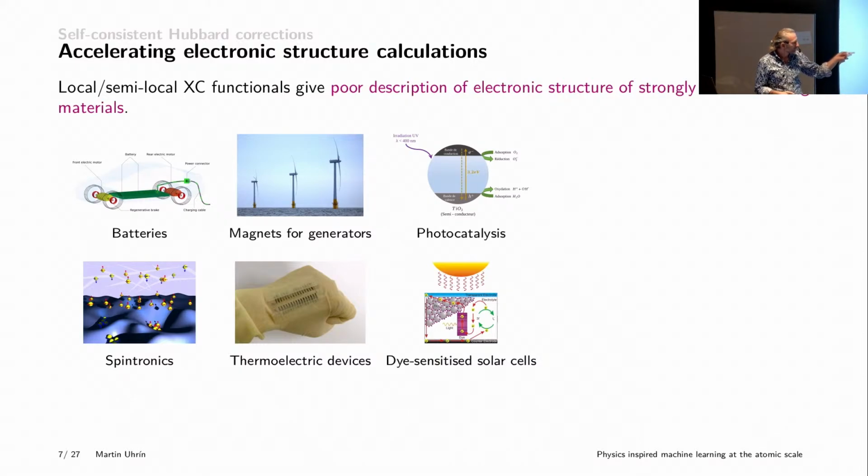One of the groups that I was in with James is very interested in electronic structure theory and pushing it beyond what it can do today. That obviously means extending it to try and fix problems where DFT doesn't necessarily work well for certain elements, certain classes of systems. One of the things we've been looking at is the electronic structures for systems that contain transition metal elements. And these are particularly poorly described in regular run-of-the-mill DFT, PBE, these kind of functionals that people tend to use. That's particularly problematic for a lot of different applications, and for us, it was particularly batteries that we were looking at.